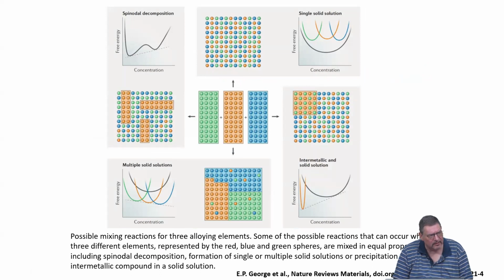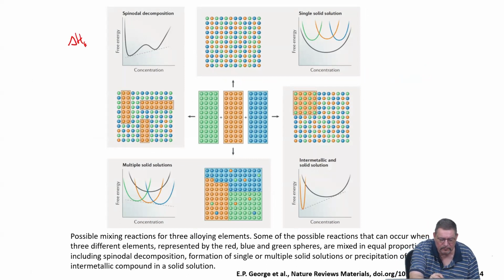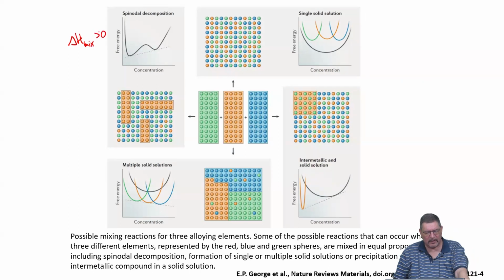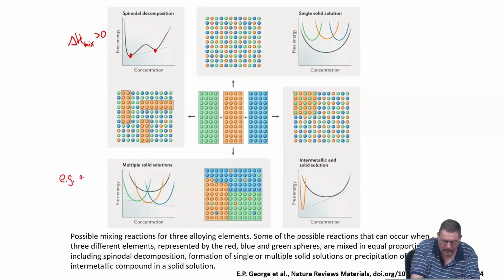I mean, if we only place 3 different types of atoms onto a common lattice, so we form a solid solution, then different processes can occur. If we have slightly higher, positive mixing enthalpy, then we can, in the solid solution, get spinodal decomposition. This means it basically forms 2 different solid solutions, different in terms of their chemical compositions, because the system would tend to go to these 2 compositions. We could have the situation that energetically it's more favorable to have more than 1 solid solution present. So this would be something like eutectic.